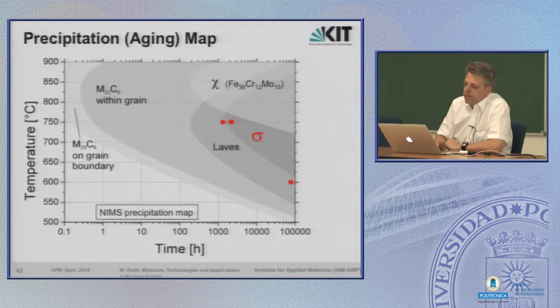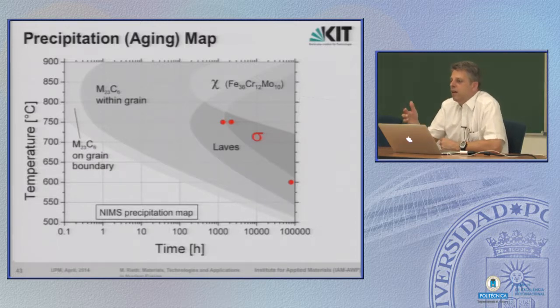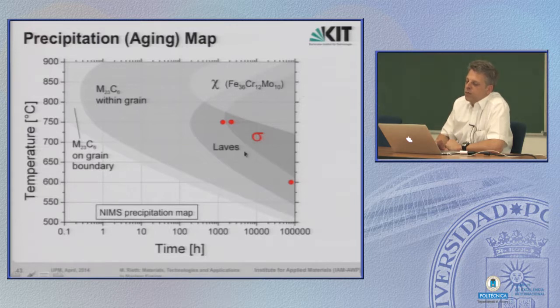And in the end, what is delivered along with this austenitic steel is an aging map. This is a map over the time, which shows you the areas in terms of temperatures and time where all these second and other phases appear. To operate this material, you should avoid all these phases completely, which means up to, let's say, 10,000 hours, you should reduce the temperatures down to 520 centigrades in this case. If you want to have it for longer times, 100,000 hours, and you want to avoid most of these dangerous phases, you have to restrict your application temperatures further. And so, in the end, the positive effect of using austenitic steels, namely the higher application temperature, is again significantly reduced if you have to use them for longer times.